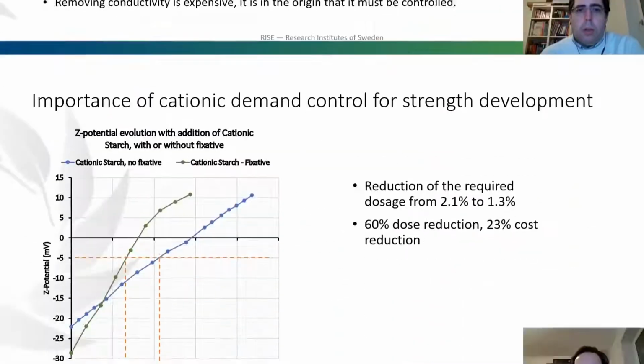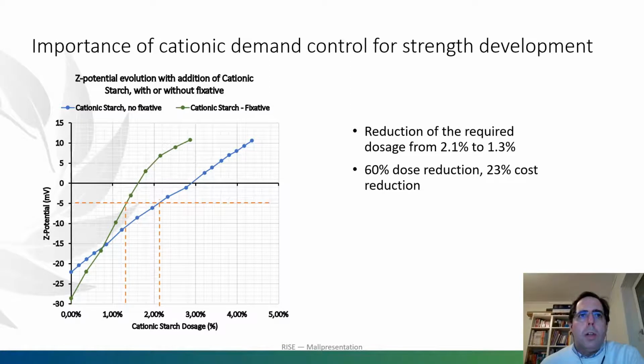But we consider, okay, how can we handle this conductivity? On the other side, we have to consider also the importance of the cationic demand, the importance of the anionic trash in the system. So now what we see in the graph is the evolution of the zeta potential, therefore the charge on the fibers, with the addition of different amounts of cationic starch. And we see two curves. The blue curve corresponds to a pulp without the addition of any fixative, so therefore without any control of the cationic demand. The green curve will be the same curve, but when a fixative has been added to the process.